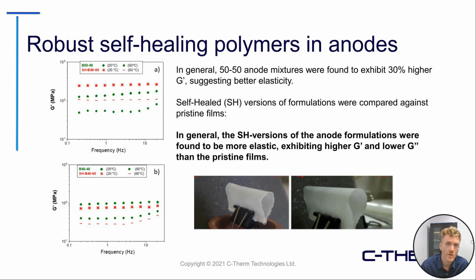But after going through a heating process at around 40 to 50 degrees Celsius, these polymers are able to reheal, re-solidify and rearrange to create a material that is even more mechanically robust than the previous pristine material. And this was found to be attributed to the anode being much more elastic, with a higher elastic modulus and lower loss modulus in the material itself.